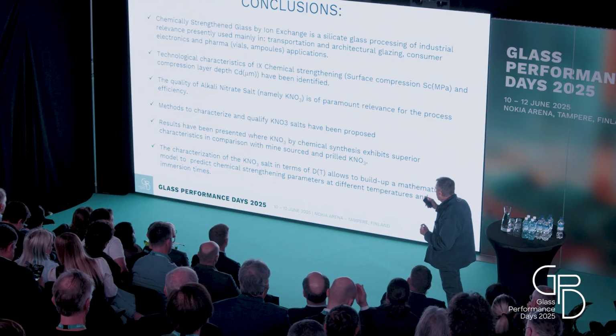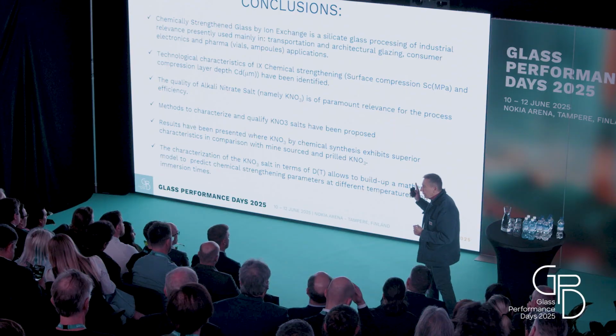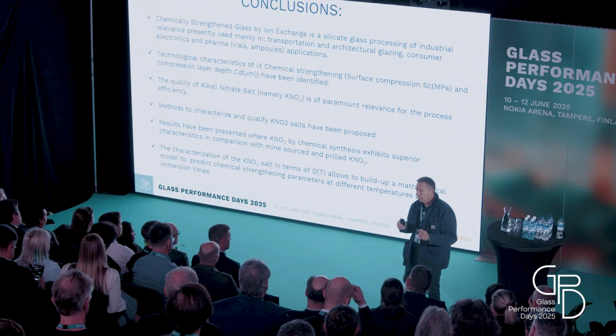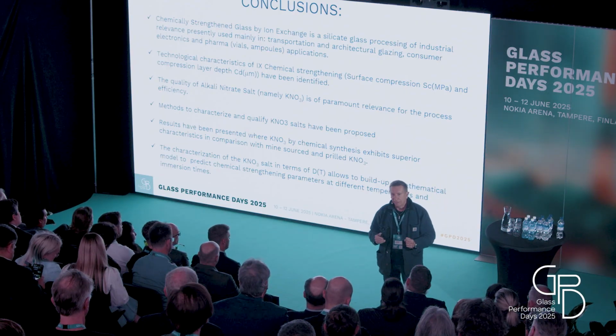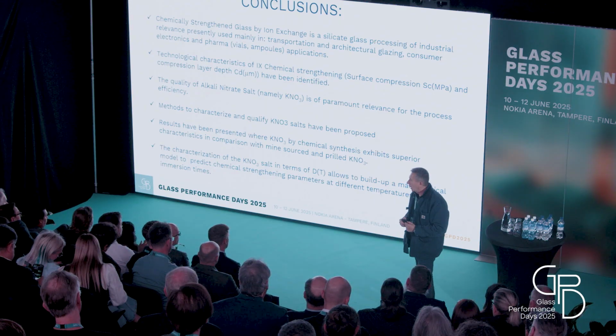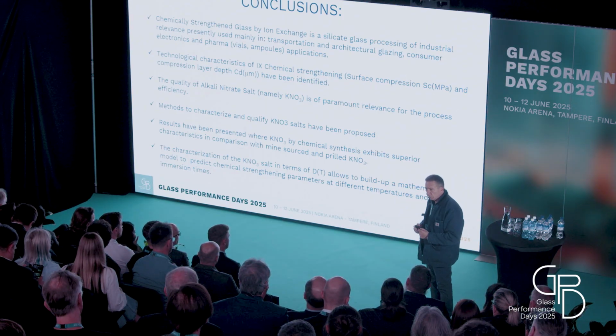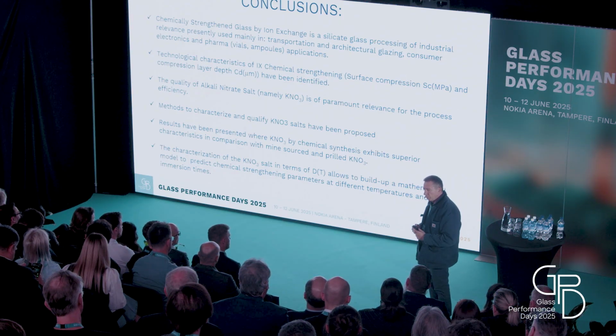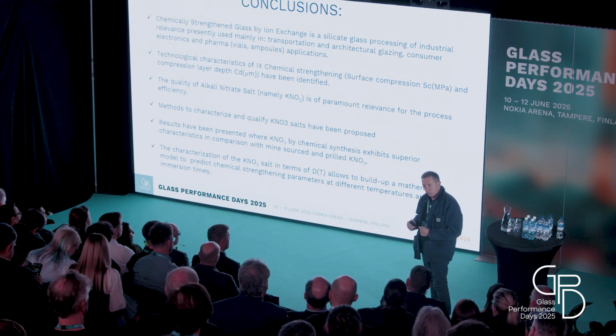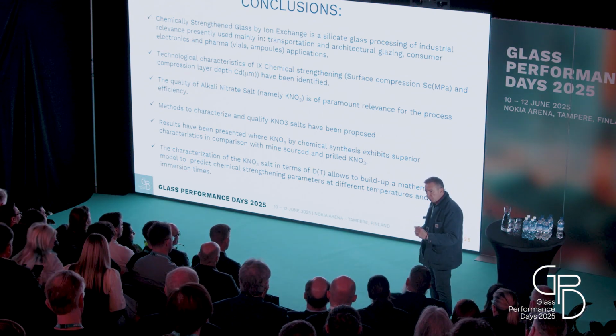Be careful of the point that in my model I have not included any relaxation effects that are indeed of relevance, especially for surface compression. Not so many, more important for depth of compression, but they are quite important, especially for soda lime glass, for surface compression. I've finished. Thank you for your attention.